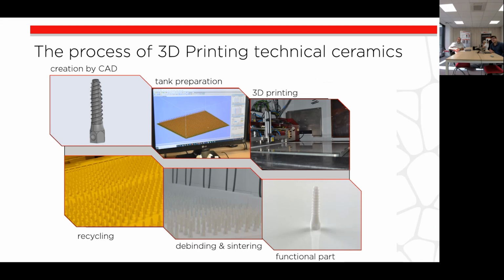The process of 3D printing technical ceramics by SLA is quite straightforward. You start from a CAD file, you then prepare a tank. That's what you see on the second picture. You then go on to 3D printing by SLA. So we do a small layer that we cure. Then we recycle all the slurry that hasn't been polymerized. We then go on to debinding and sintering to obtain the functional, final part with the correct dimension and density.